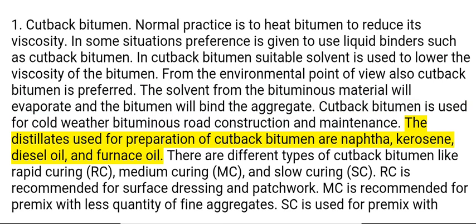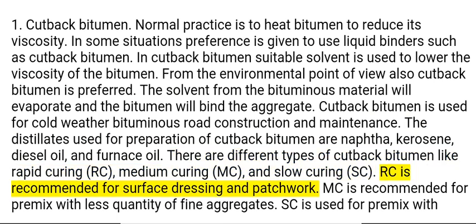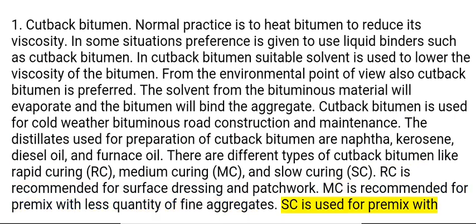kerosene, diesel oil, and furnace oil. There are different types of cutback bitumen: rapid curing (RC), medium curing (MC), and slow curing (SC). RC is recommended for surface dressing and patchwork. MC is recommended for premix with less quantity of fine aggregates. SC is used for premix with appreciable quantity of fine aggregates.